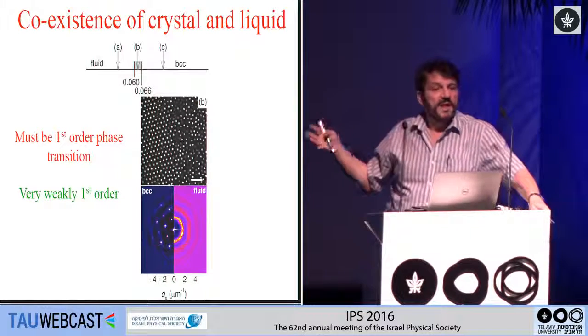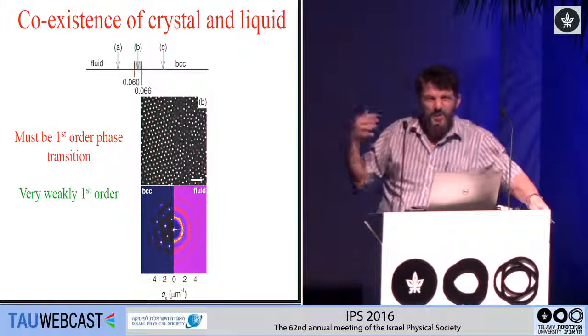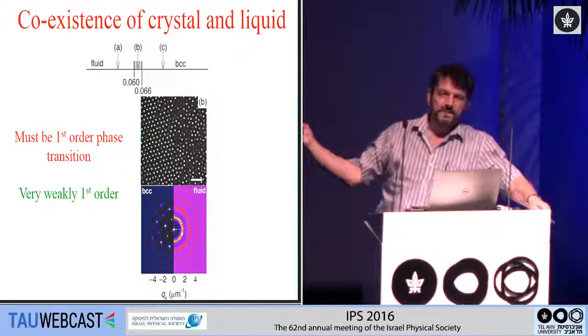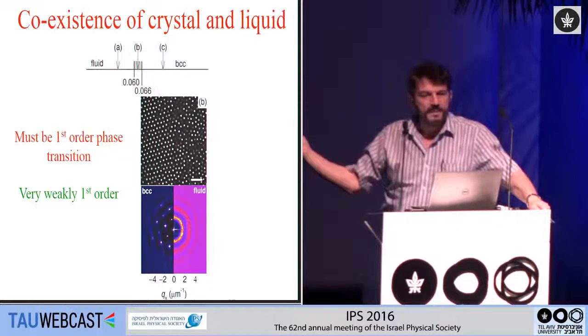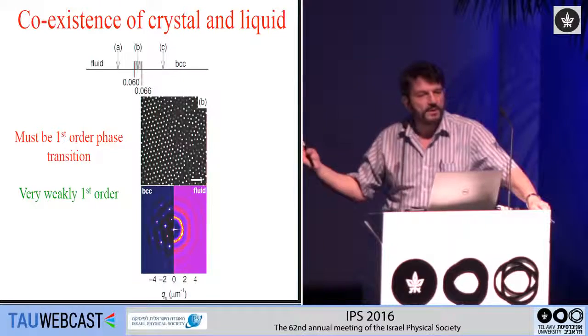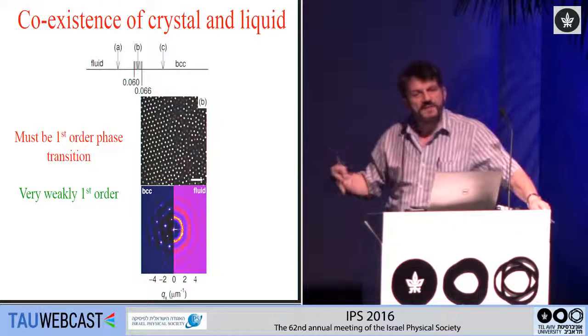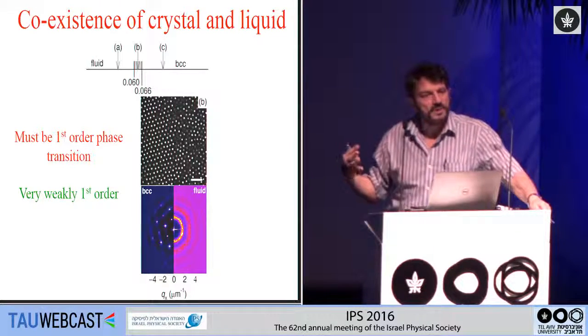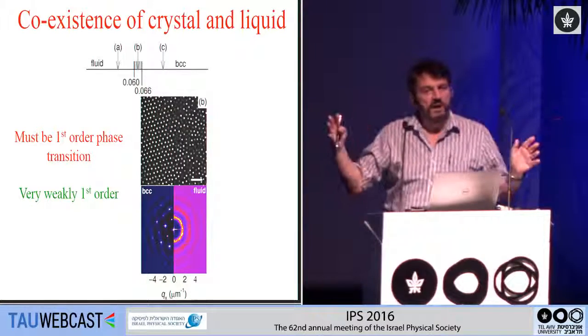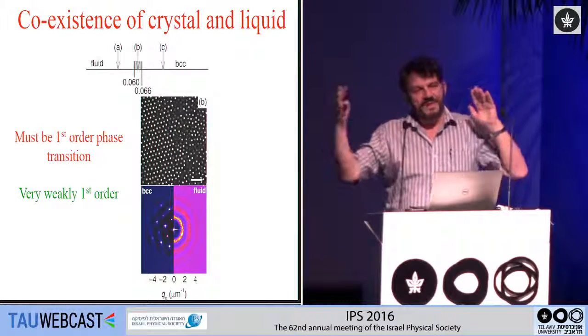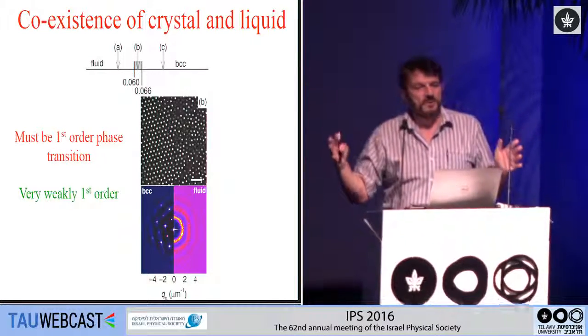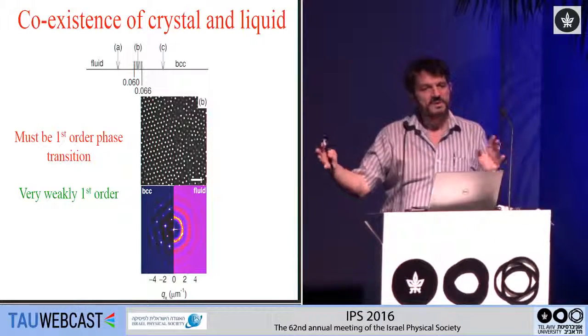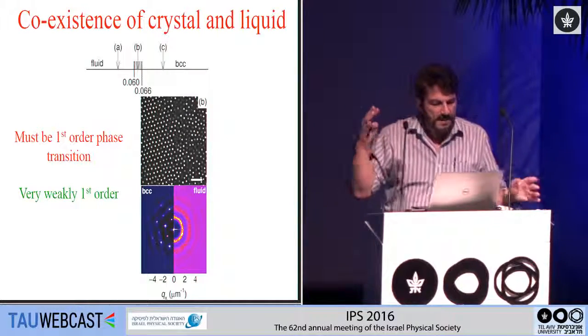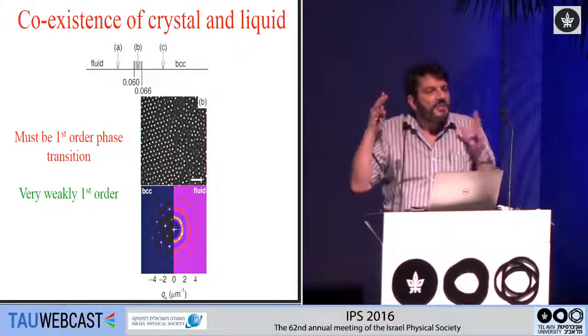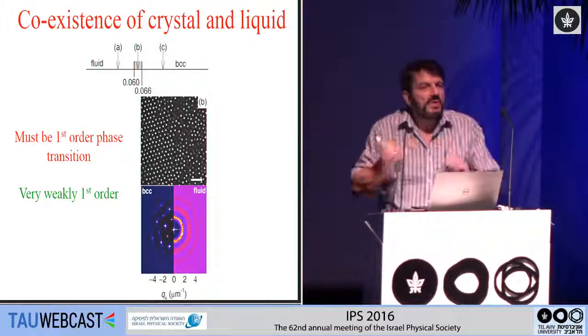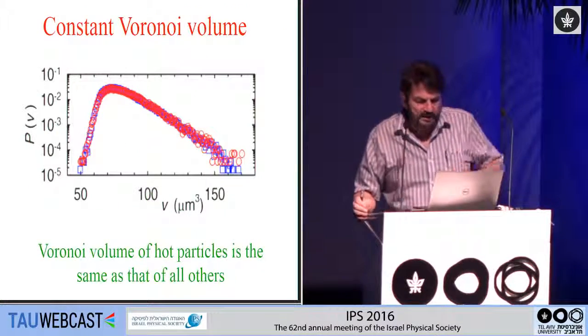And we looked very carefully and asked the question, well, are we really seeing a coexistence? Could it be that there was some time evolution and we didn't quite reach equilibrium? But we convinced ourselves that in fact there is a strong coexistence. So we see this dichotomy. We see something that is clearly a first order behavior, clearly has a coexistence between a liquid and a solid, but nevertheless has this critical-like behavior. So it's only weakly first order. So how can we understand that?